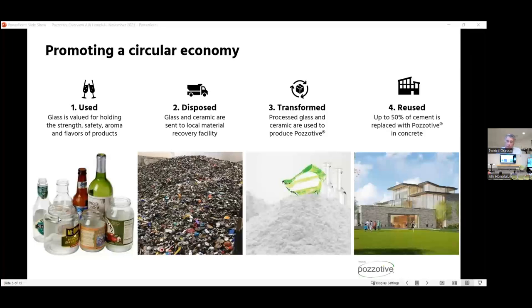That photograph on the right is New Canaan Library. So local Connecticut glass processed in Connecticut, given to a local ready-mix company here, and then back into a project from the community from which it came. We can replace, we've done testing to replace up to 50% of cement in concrete. Commercial use typically is probably more in the 25 to 40% range as we're seeing today.